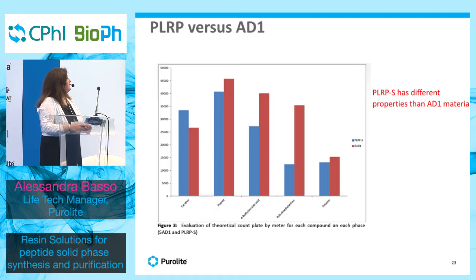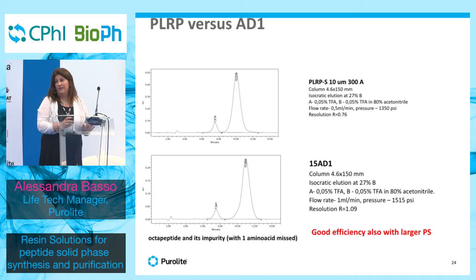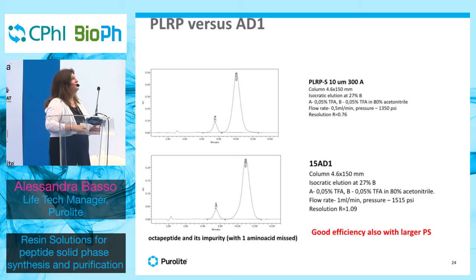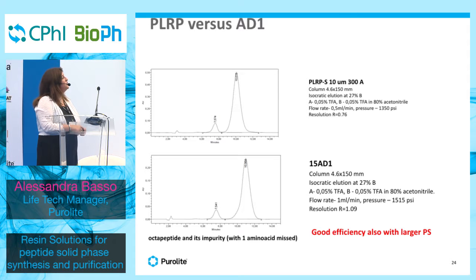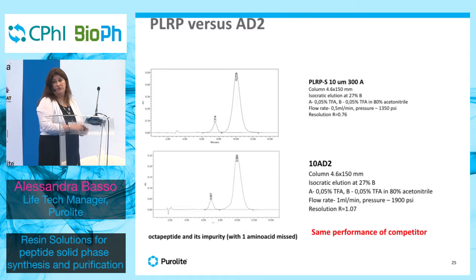This is again a selectivity of our AD1 against the PLRP. This is some example of amino acids. You will bear with me. We are not peptide manufacturers, so we do very basic examples. I know that in the market and in production, you do much more complex molecules. But this was to show you really what is the difference between our material and competition. In our case, with the 15AD1, even if the particle size is larger, because it's 15 micron compared to the 10 micron, we have an excellent separation between the two peaks.